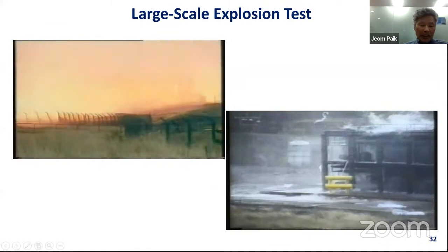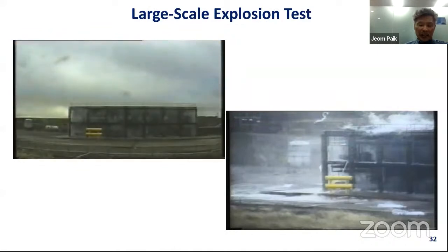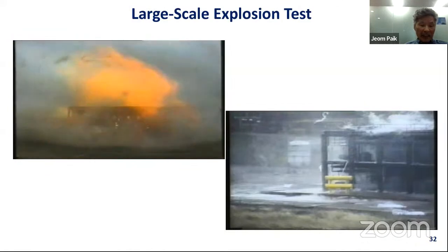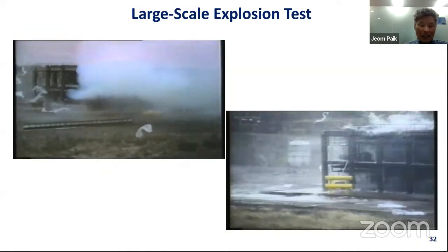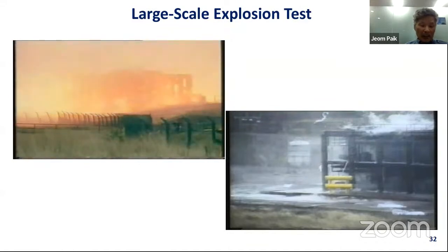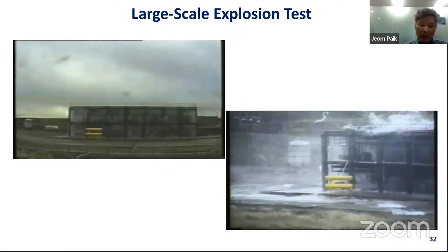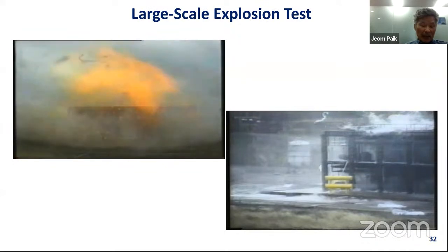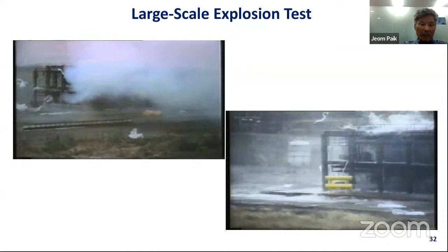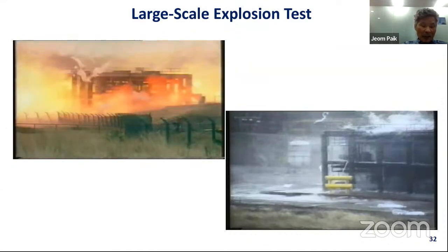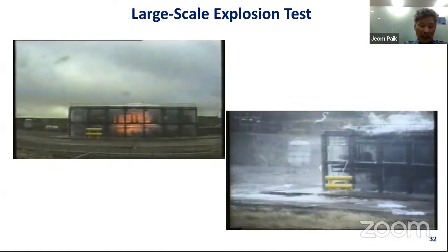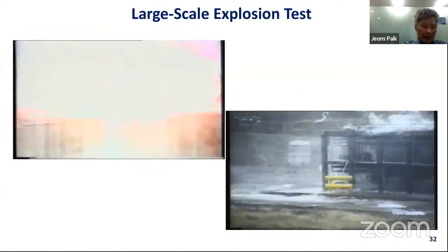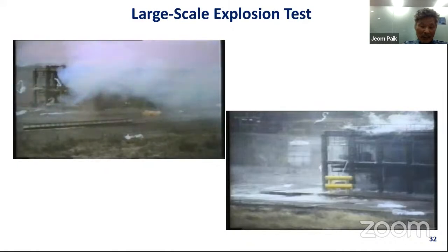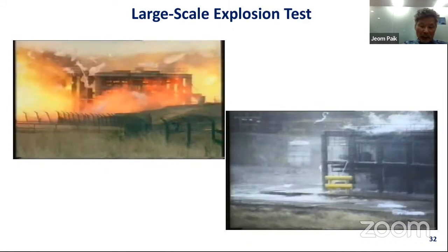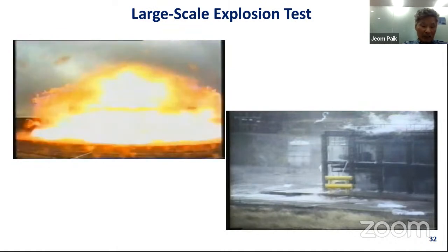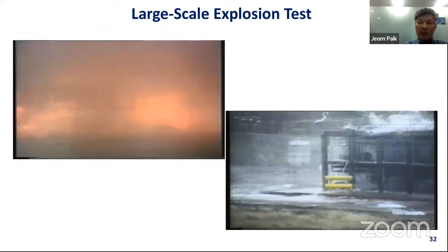In order to mitigate the blast pressure loads owing to explosions, water spray is usually applied as a safety measure. The left-hand side test did not apply the water spray, and the right-hand side test applied the water spray. By comparing these two tests, you can see that the yellow bar structures outside the test frame in the explosion did not survive on the left-hand side test without the water spray safety measure, but they survived on the right-hand side test with the water spray. This is because the water spray application decreased the blast pressure loads owing to explosions significantly.